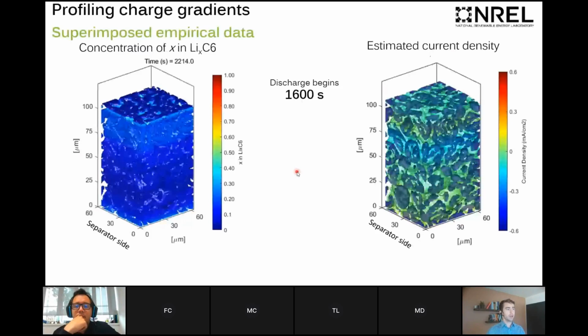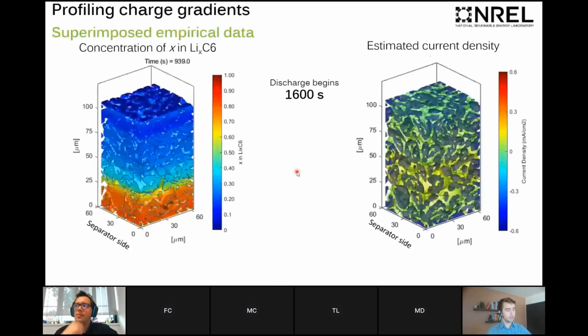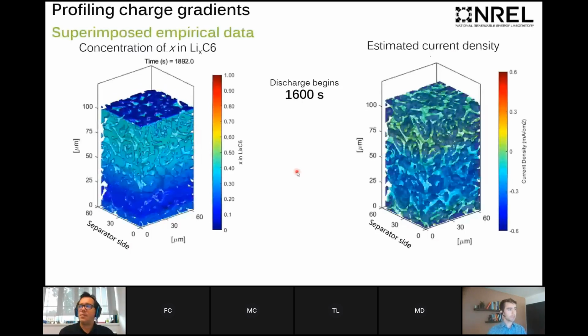And so we can relieve lithiation gradients by improving the ionic conductivity and transference of the electrolyte, decreasing the thickness of the electrode, which we don't really want to do because it affects the energy density of the cell, or we can reduce the tortuosity of the electrode.